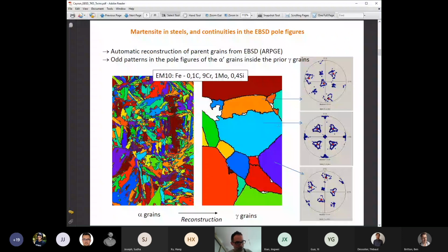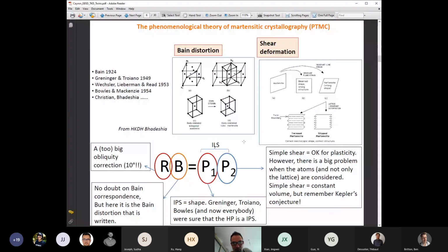I looked at the literature at that time, and there was a theory called the phenomenological theory of martensitic crystallography. It is based on the question of how to transform an FCC, face-centered cubic phase, into BCC, body-centered cubic phase. On the left part, the Bain distortion, there is a cube that is represented alone. It's an FCC. When you put two FCC cubes side by side and look at the cell in the middle, with the vectors B1, B2, B3, it is a tetragonal cell.